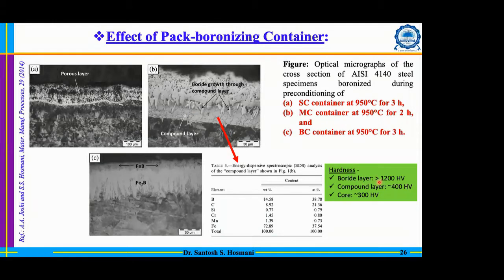But this is not really the boride layer, because a boride layer has a hardness typically greater than 1200 HV. So definitely that is not in the category of boride, but a compound layer is forming initially. And here you can see that the sawtooth morphology is actually emerging in this compound layer.